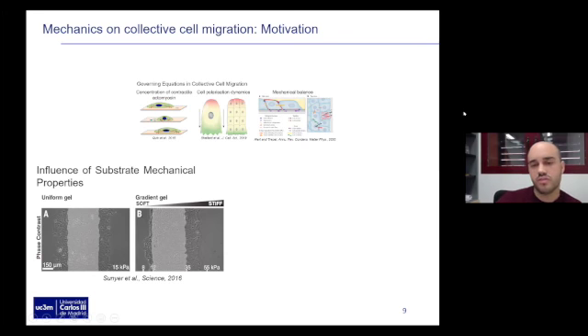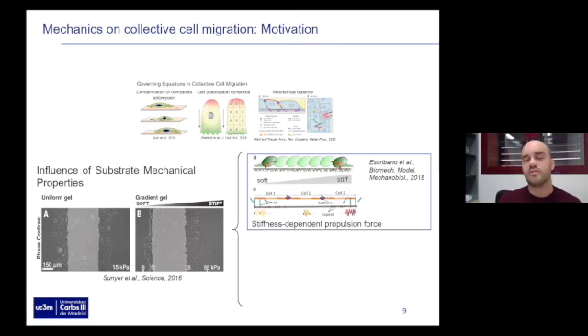So when we look into the literature, most of the experimental works and even some nice modeling frameworks suggest that this is somehow a kind of stiffness-dependent propulsion force. As our system is connected by focal adhesions to the substrate, we can expect higher interaction forces in that stiffer region than in the softer one, so that we're going to have a resultant force directing the migration to that region.